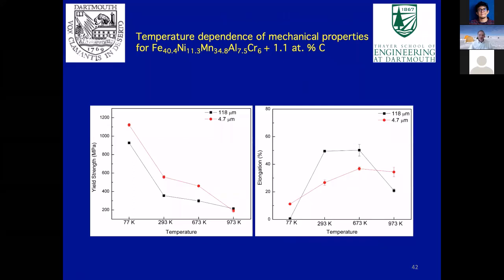We also looked at the temperature dependence of the mechanical properties, only for the carbon doped alloy and for two different grain sizes. If we look at the yield strength, you can see as you go up in temperature, the yield strength goes down, which is what you'd expect. The yield strength actually goes down more rapidly for the fine grain size material. We may even be getting some grain boundary sliding at this temperature, that's why it's weaker.